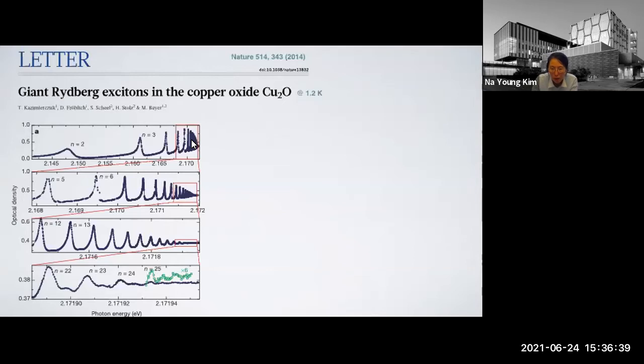If you're in the exciton business, you may sense that n equals 25 is actually amazingly high. It's much smaller than the atomic counterparts like 70 and 80. But in fact, because of the material host, even n equals 25 of the Rydberg exciton gives very competitive optical properties compared to Rydberg atoms in the 80s and so on. So this is truly giant Rydberg excitons.